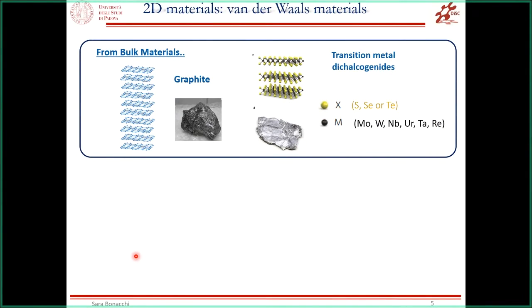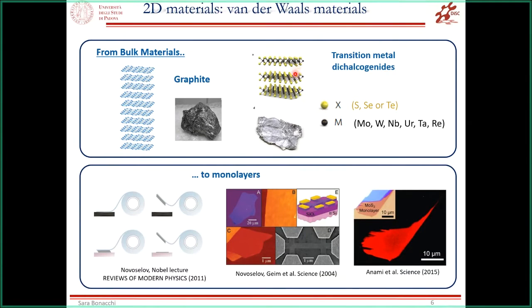And so for the people that are not familiar with van der Waals heterostructure, we have to consider that when we talk about van der Waals material, we're talking about something like a graphite or transition metal dichalcogenides, whose properties are very different when we pass from the bulk material to the monolayer. As you know, starting from the Nobel Prize in 2010, especially the physics committee start to be very interested in this 2D material, and whose properties are very affected by the fact to be monolayer. So Novoselov got the Nobel Prize because he was able to use this Scotch tape approach to form a monolayer film of this 2D material.